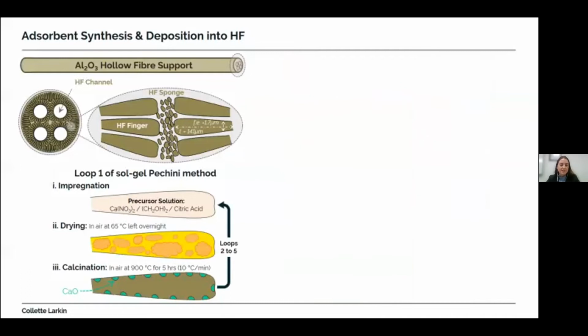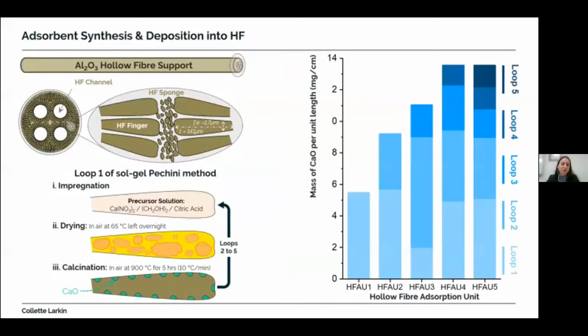To investigate this, we developed 5 hollow fibre adsorption units and tested those, with the number of impregnation loops increasing incrementally with each subsequent unit. This bar chart shows the amount of calcium oxide deposited per unit length of hollow fibre for the 5 hollow fibre adsorption systems. After 4 and 5 impregnation loops, we can see that the amount deposited has plateaued, indicating that the fingers were likely saturated with calcium oxide.